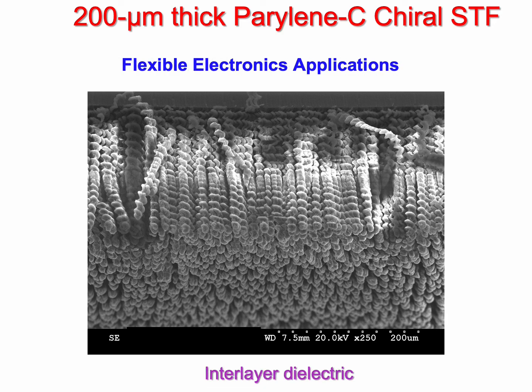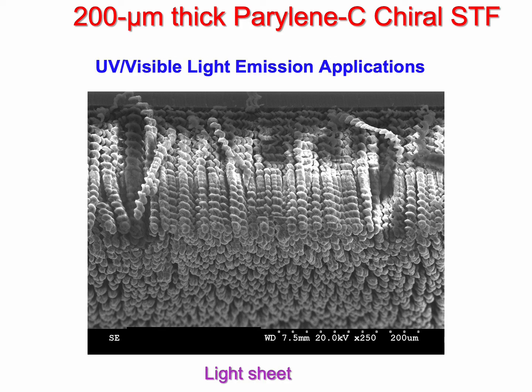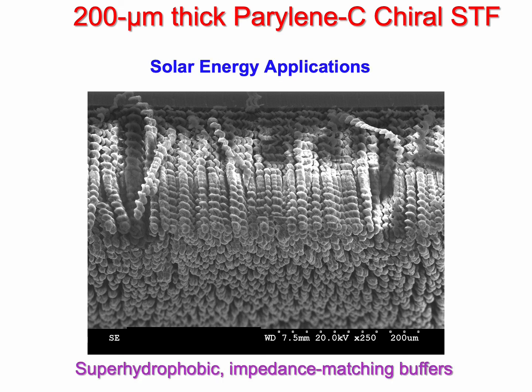One of my students evaluated these thin films as interlayer dielectrics for flexible electronics. Then the material can withstand repeated mechanical and electrical loading and unloading. After impregnation with quantum dots, these films can emit visible or ultraviolet light, according to theory. But that is not all either. These films could also function as superhydrophobic impedance matching buffers for photovoltaic solar cells to thereby increase the efficiency.